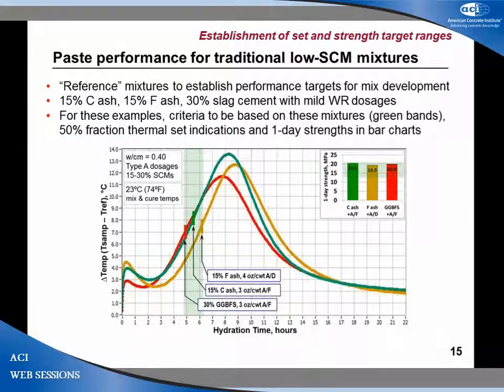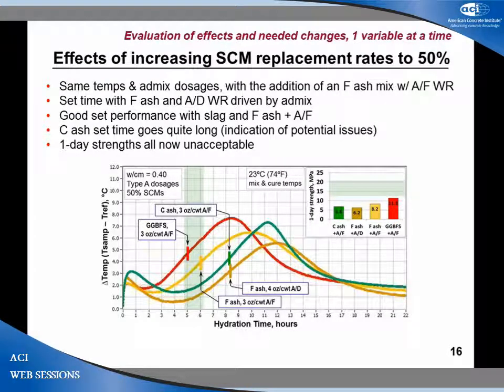Later on, since our objectives are to make this a 50% cement replacement mix, what happens when you do nothing but change the cementitious mixture to where you have 50% total cement replacement? And obviously, particularly in the case of a mix with a type A D or a common lignin type admixture, that goes long. In the case of the polycarboxylate admixture with the F ash, it's still hanging in there on the setting time. But now our C ash mix is beginning to produce setting time issues that we're going to have to watch in this process. Obviously, our one-day strengths are all well below the target band now.